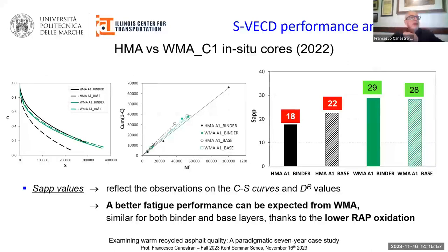In this slide, we have the summary of the experimental results obtained with the FlexMAT, expressed in terms of pseudo stiffness curve, DR parameter, and synthetic index Sapp. Based on Sapp values on the right, we can observe better fatigue performance for warm mixtures, both in the case of binder and base mixtures, translated by higher values for the Sapp parameter. This result can be due to the lower aging oxidation in the case of warm mixtures.